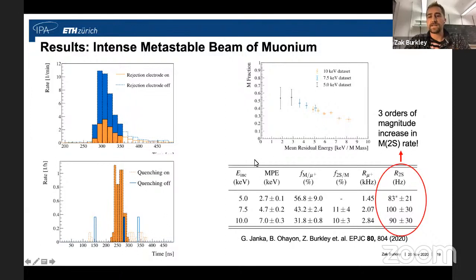And after taking into consideration all of our detector efficiencies, we were able to estimate that we're actually producing about 100 muoniums per second in the 2s state. This is 3 orders of magnitude better than what has been used in the past for muonium Lamb shift measurements. So we're very excited to try this Lamb shift measurement here in 2 weeks and hope to see some really good statistics.